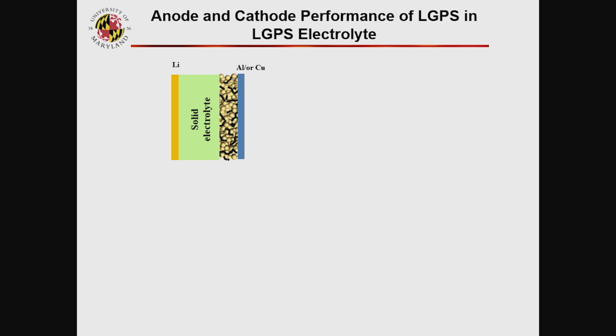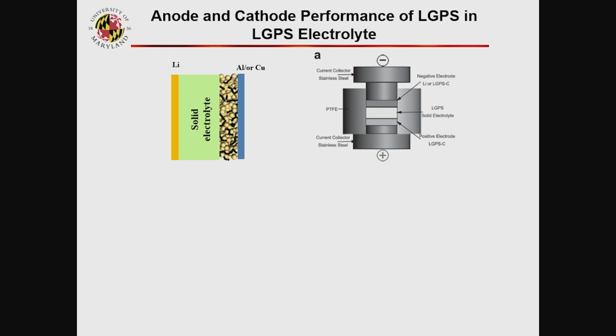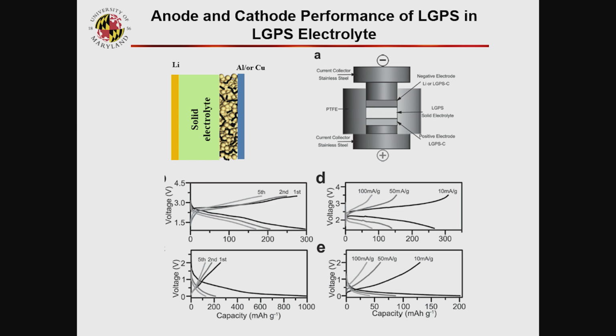We want to build a solid state. We have to change this electrolyte as a solid state, meaning we use exact same LGPS. So this LGPS mixed with carbon. And then we test it again. We just press it. And then we check the charge discharge at high voltage, charge discharge at a different cycle. This charge discharge at a different current. And this is at a low voltage. So this will test the cathode performance. This is anode performance. Solid LGPS, the performance is same as we test in organic electrolytes.